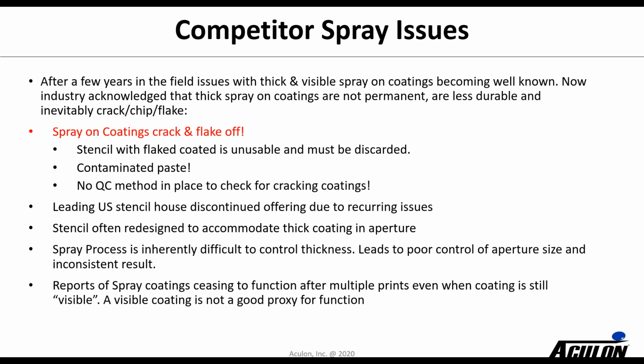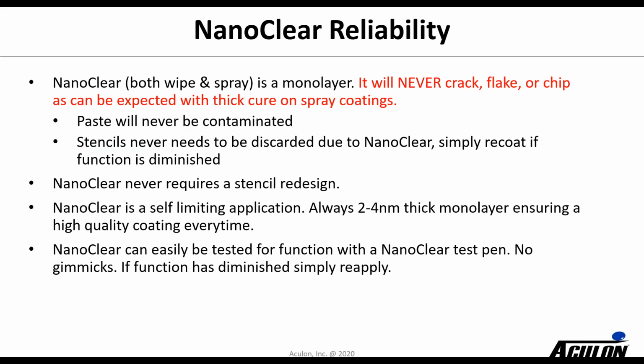So as mentioned in the previous slides, we are offering our own spray version for those of you that are concerned with these issues and are looking for a spray applied coating that mitigates these issues. So to cover NanoClear's reliability and durability in these next two slides, both the wipe and spray variant of NanoClear are monolayer, so it will never crack, flake, or chip like you might see with a competitive coating. It will never contaminate the paste, and the stencils will never need to be discarded due to NanoClear. As long as the stencil is mechanically sound, you can recoat with NanoClear as many times as you need. NanoClear will never require a stencil redesign, and it's extremely reliable, both in the wipe and spray format.